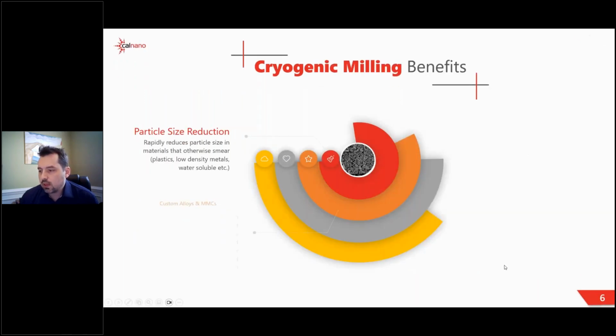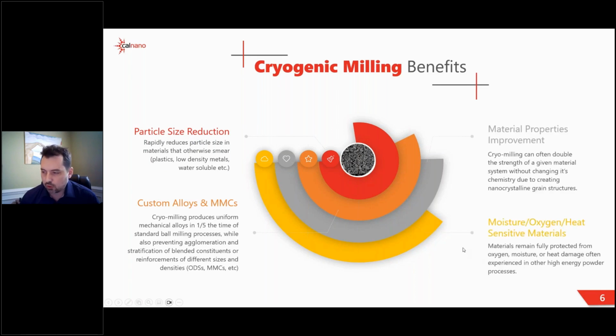So what benefit do you get and why would someone do this to a material? So I'll start off with the most basic and arguably maybe the most boring, which is just standard particle size reduction. In many cases, materials come in a powdered form, but someone needs them in a finer powder, but that material doesn't want to break down or get ground very easily. Sometimes that's a function of the material's low melting point where it likes to re-agglomerate or melt and become a bigger agglomerate. Sometimes it's just that the material is very tough, and so rubbers and materials like that have a high toughness that can kind of rebound any cutting and grinding that you might try to do to them. And so those are usually the issues.